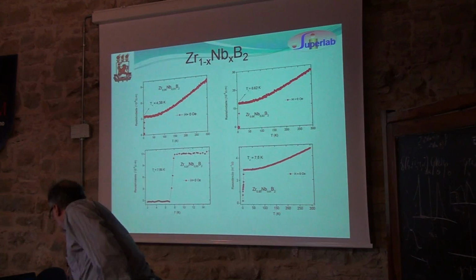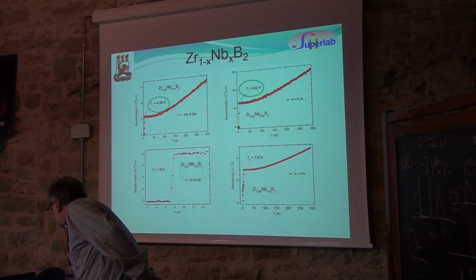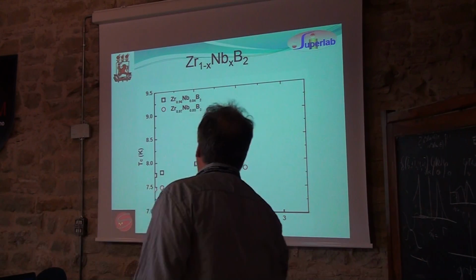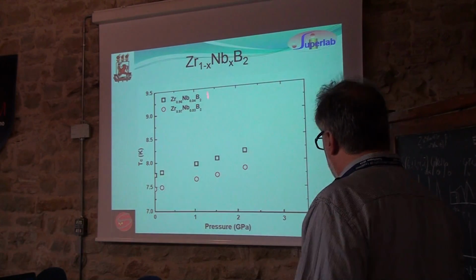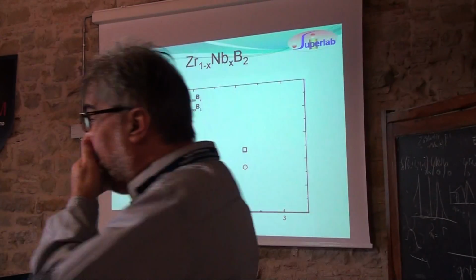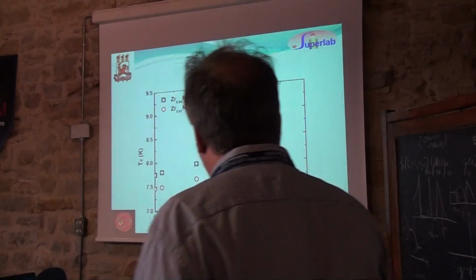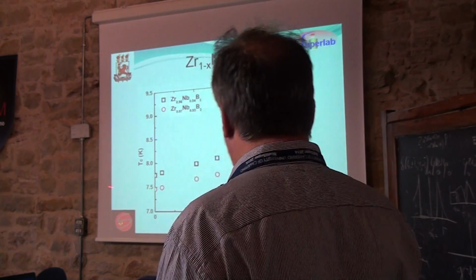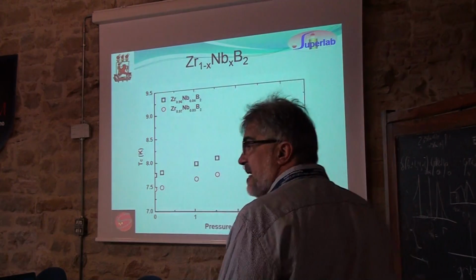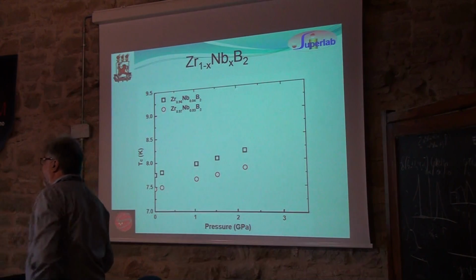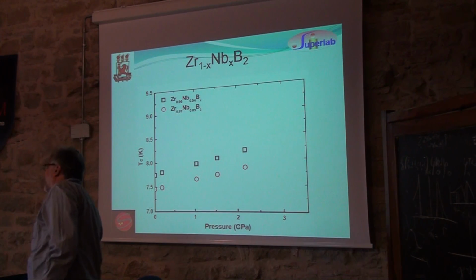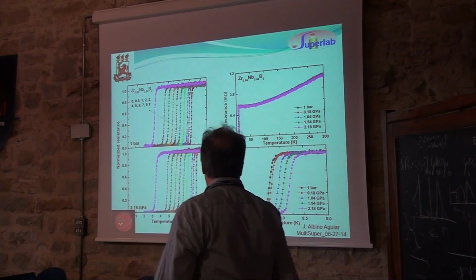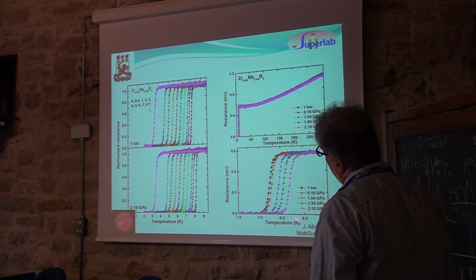And finally, let me show the transition temperature. We decided to study the pressure dependence of the temperature. And we have for two samples, niobium doped, and they have the same dependence. And we have a change of 0.5 K. Arkady is trying to model this. And here are the data. You see that it's quite robust.